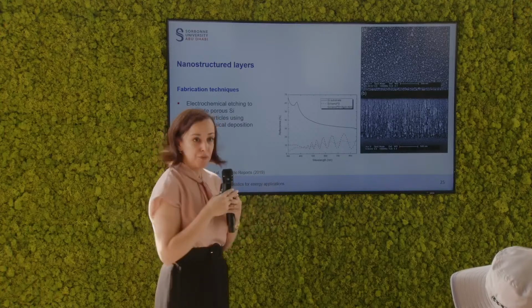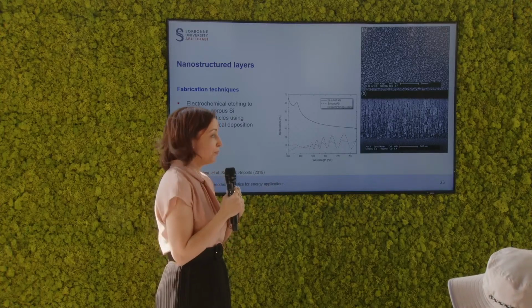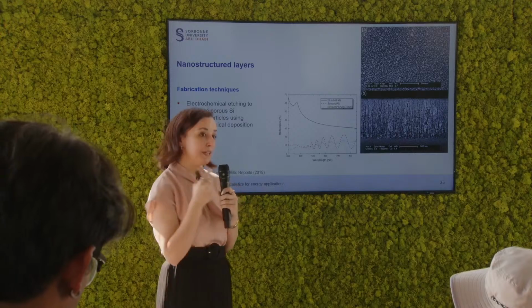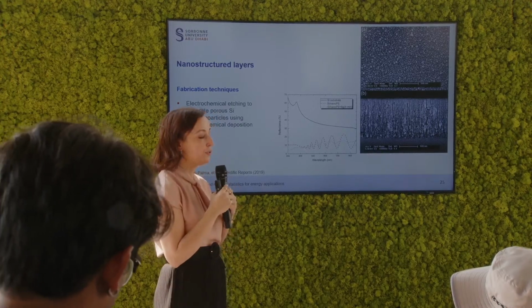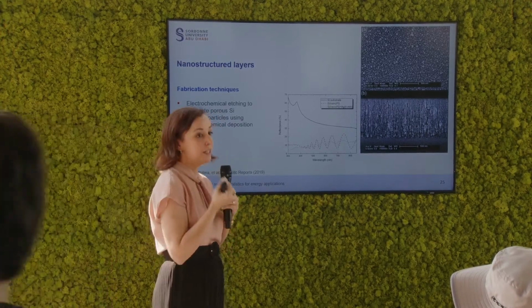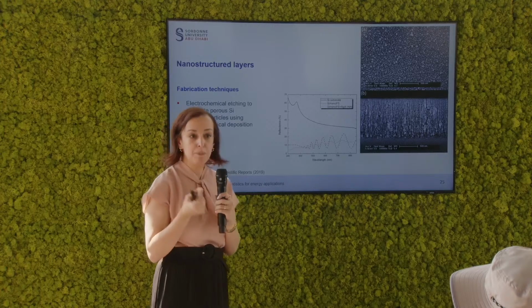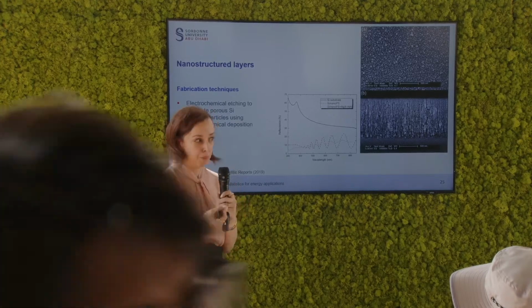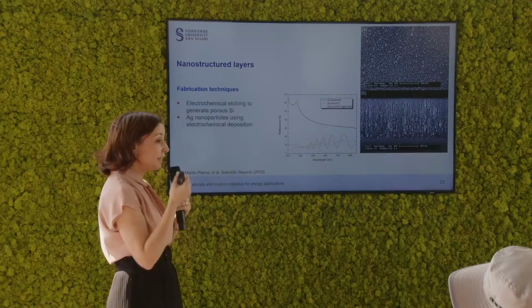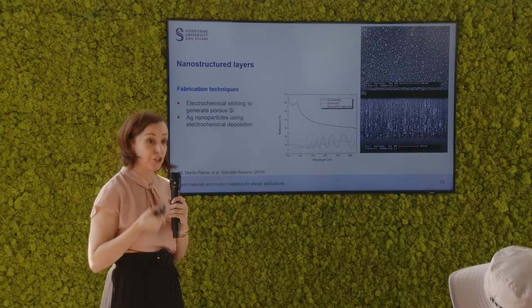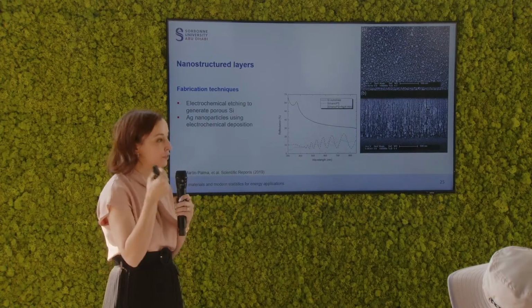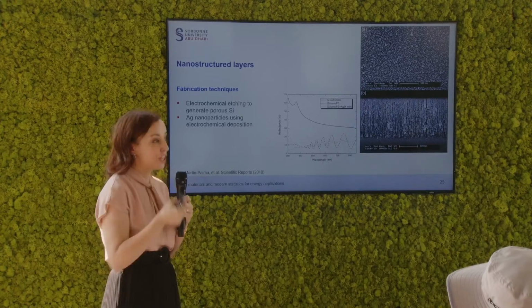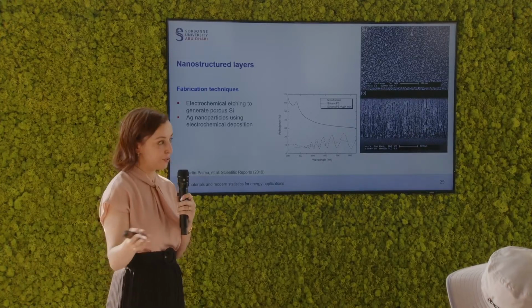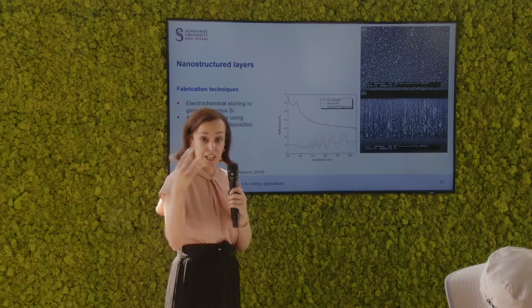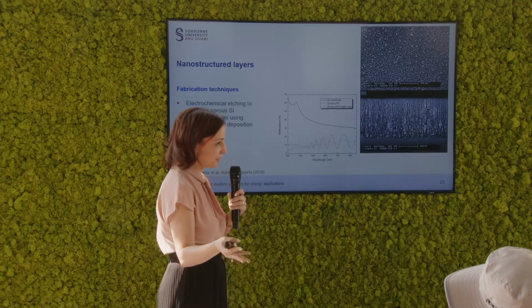Even though it's a successful process when it comes to lowering the reflectance, the one disadvantage of this is that you start with a crystalline silicon wafer, which is not a cheap material to start with in the first place. And you electrochemically etch that material, which means you're eating away the surface of that layer. So you're generating material waste as well. So you start with an expensive layer, and you eat it away to generate the porous layer.